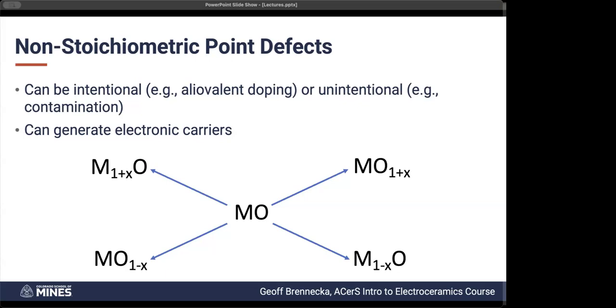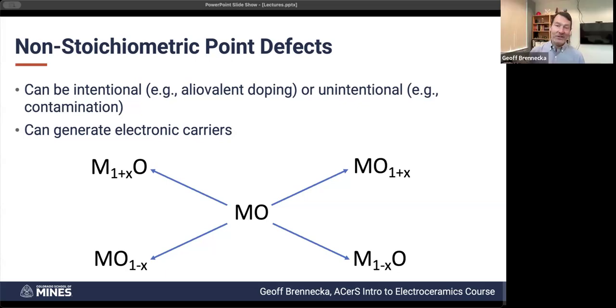So if we were to apply a field to the Schottky or Frenkel defects, would an interstitial or a vacancy have a higher mobility? That's a great question, and that depends entirely on what the material is. So, for example, if it's a lithium interstitial, it's probably going to be pretty easy to move because lithium is only +1. It's not a huge ion. It's how battery electrolytes work, because you can move lithium ions around.